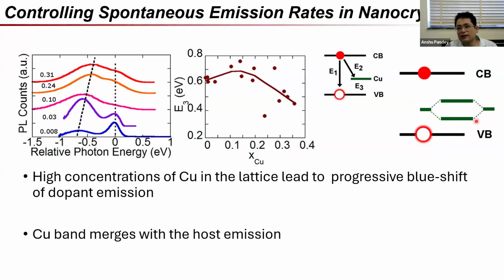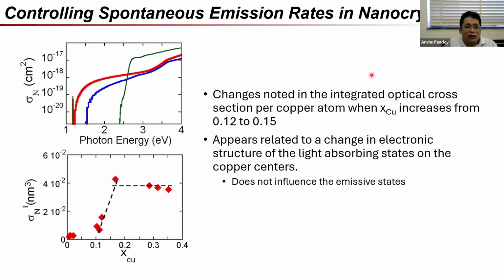And this state is responsible for the entire effect, because it is carrying all the oscillator strength, and we go blind to these higher energy states. So there are other consequences. There are some unusual things which copper does, which we understood only in part. It seems to radically change the spectroscopy of the material right around 15% loading levels, which we don't understand at all, because it does not seem to be related to anything physical that should be happening.